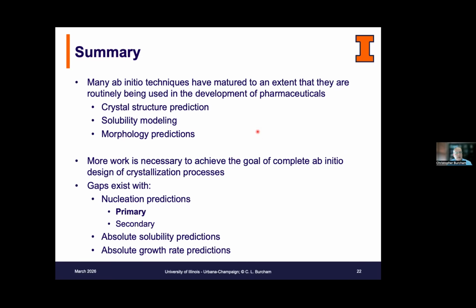So, to summarize, these ab initio techniques have matured to an extent that they're very routinely being used in the development of pharmaceuticals. However, they're being used in discrete instances. If we want to achieve the goal of complete ab initio design of crystallization processes, we found that the biggest gap exists, as one might expect, in the nucleation predictions, and especially with primary nucleation, because it's hypothesized that that's what's dictating which crystal form of those predicted by CSP is going to be the most likely to be observed experimentally. And then secondly, the ability to predict absolute solubility and absolute growth rate.